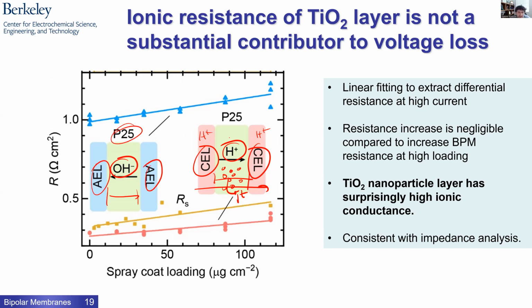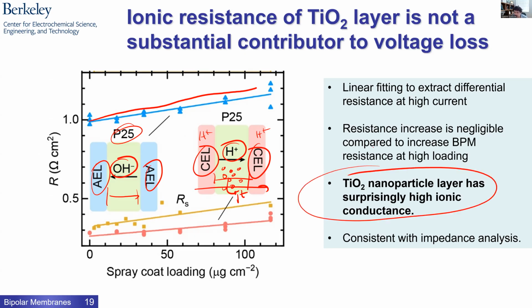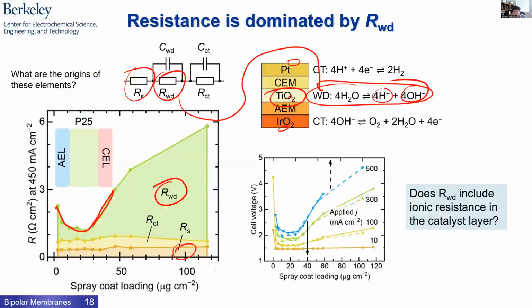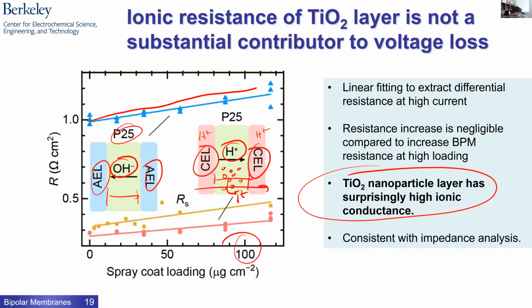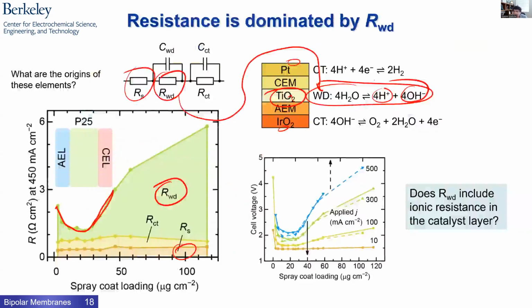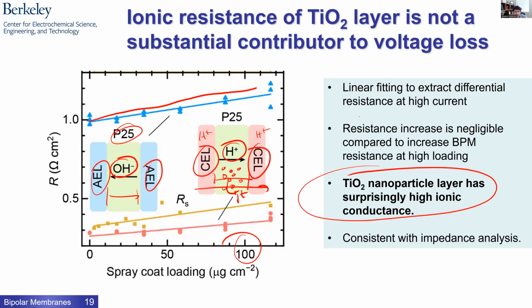This is P25, the label. It's Degussa P25 TiO2. It's a good standard for TiO2. Everybody has it. And what you get here is the slope, and the slope tells you the conductivity of hydroxides and protons through that TiO2 layer. What's interesting is the TiO2 layer has surprisingly high ionic conductance for both. So you can go to very high loadings, and you don't get a big ohmic component to your resistance. So it really must be, again, something to do with this reaction. So why would that reaction slow down?